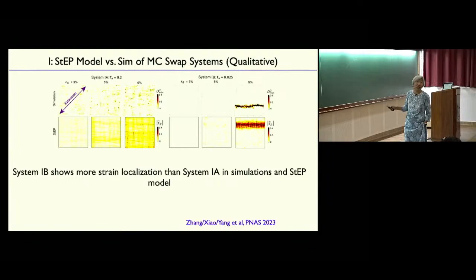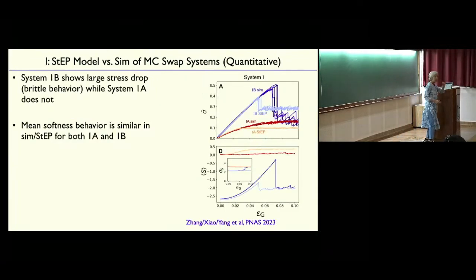You also see that in the step model. So pretty good. And then this is the experiments. Oh, no, sorry. This is a quantitative comparison. Here's the stress-strain relation for the first case, more ductile, the simulation versus the step model. And the second case, more brittle, the simulations versus the step model. And the average softness, again, reasonably good, and the standard deviation of softness. Okay, so reasonable quantitative agreement.